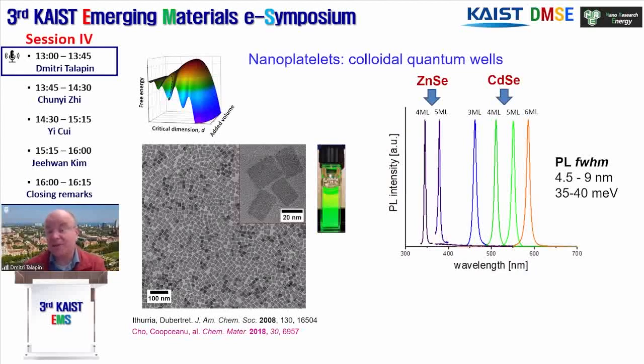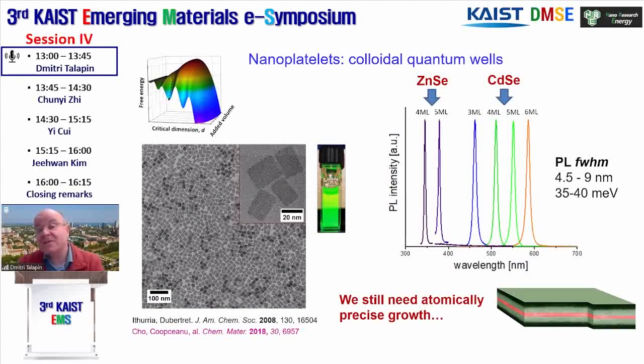We don't need to have something like graphene or molybdenum disulfide, where chemical bonding is special, such that the crystal is forced to grow, let's say, in two dimensions. In this case, we can apply it to crystals with cubic crystal structures, such as zinc selenide or cadmium selenide. And by navigating the solution, by controlling temperature and reagents, into one of these side valleys, we can grow ensembles of particles where every particle will have exactly the same thickness. For example, like in these platelets, and we have a full flask of them, so we can scale it as much as we want. And we can grow selectively populations of particles with different thicknesses. So it works surprisingly well and can be controlled with a very impressive degree of precision.